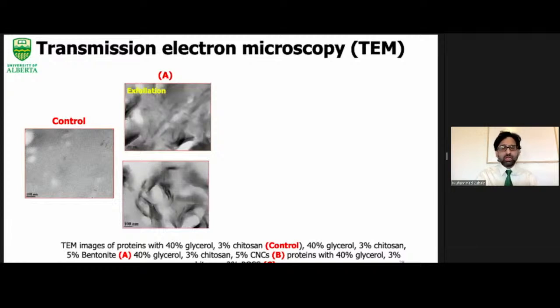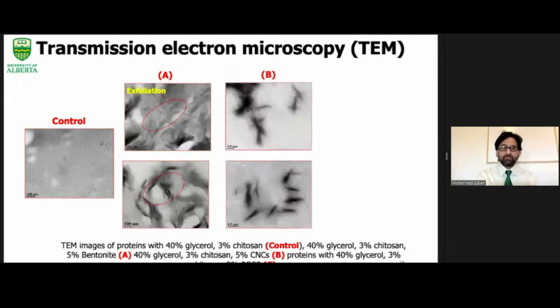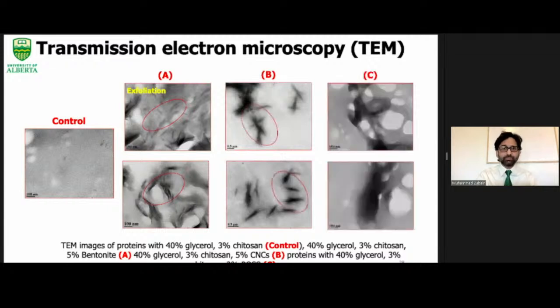The A belongs to the protein films containing bentonite. In this case, we can see that either the nanoparticles are exfoliated or intercalated. However, in case of protein films containing cellulose nanocrystals, mostly aggregation can be seen. And in the third case, the film containing POSS, we can see the introduction of black spots that show the presence of the silicon atoms in case of POSS that has been introduced into the protein matrix.